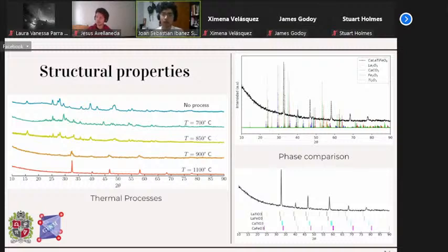And we, in particular, made a qualitative analysis. We compared our last diffractogram with the precursor oxide, which is the image that you can see at the top right, to ensure to a certain extent that we didn't have a lot of precursor oxides left in our sample. And we also tried to compare how the peaks of our material compared with the possible secondary phases, in particular CaTiO3 or the titanium calcium, I don't remember, that we expected or wanted to add up to CaLaTiFeO6.